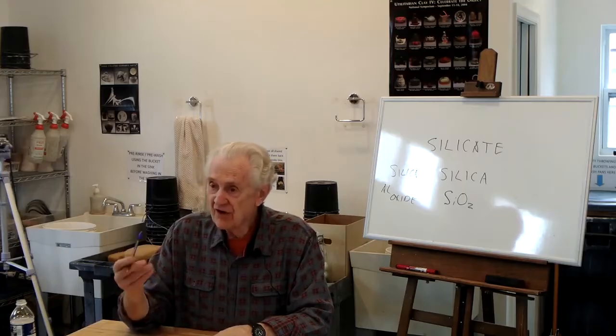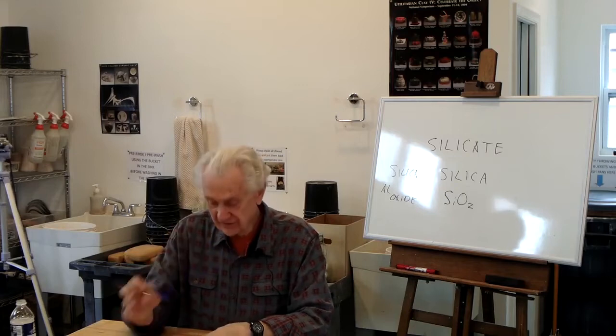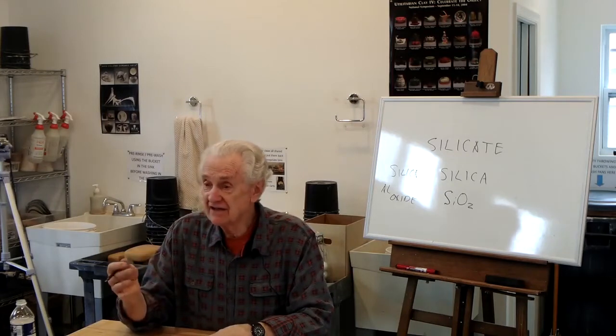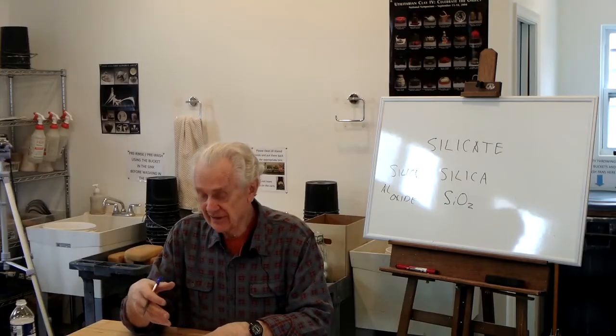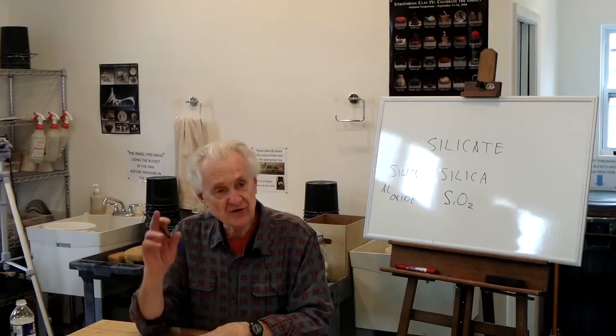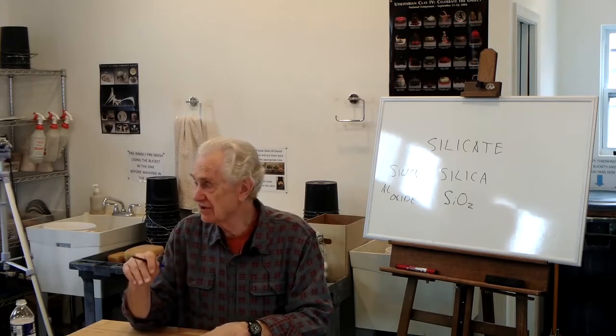So those properties are all controlled by the proportions and the identities of those materials in those 3 groups. Whether it's glossy or matte, we're talking about essentially the base glaze now, that's determined by those ingredients. Whether it's clear or opaque, that's determined by the ingredients. What the color response is. We have that list on the previous page of all those different fluxes. They affect how a colorant interacts with the glaze. So the copper in the presence of lithium flux is not going to give you the same color as copper in the presence of sodium.